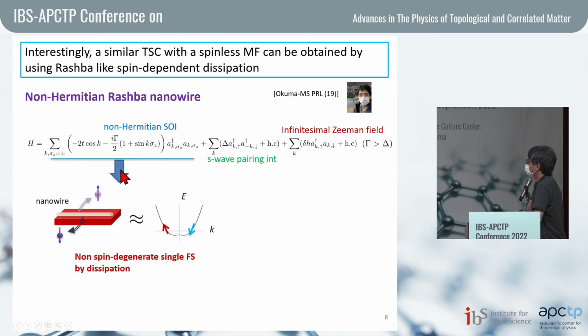So we have this kind of picture. Because of this spin-dependent dispersion term, the forward up-spin electron and the backward down-spin electron decay. So we effectively realize this situation: only the forward down-spin electron and the backward up-spin electron survive. This means that we can effectively realize a non-spin-degenerate single Fermi surface using these dispersions.